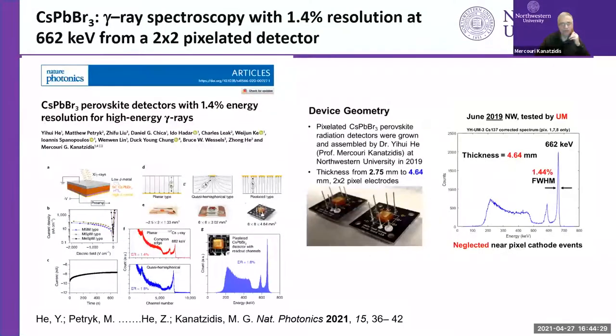for many applications. We then made pixelated detectors. And with pixelated detectors, one can actually control better the applied field inside the crystal. This is basically a very small 2x2 pixelated detector. In other words, it has 4 pixels. This was done in collaboration with Professor John He at the University of Michigan. And when we did that, we got much better resolution than before.